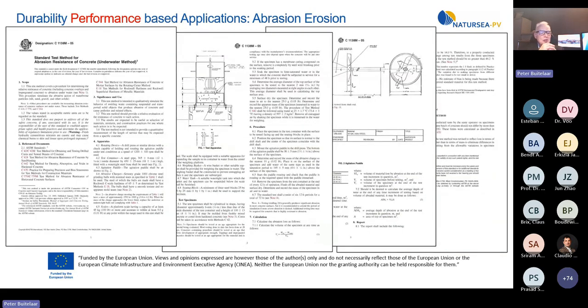The underwater abrasion resistance test, ASTM-C 1138, evaluates the durability of concrete surfaces when exposed to hydraulic forces and suspended abrasive materials, as commonly encountered in hydraulic structures. The test quantifies the abrasion resistance by measuring the mass loss of a concrete specimen subjected to a rotating propeller in water containing abrasive particles, steel balls with different diameters.